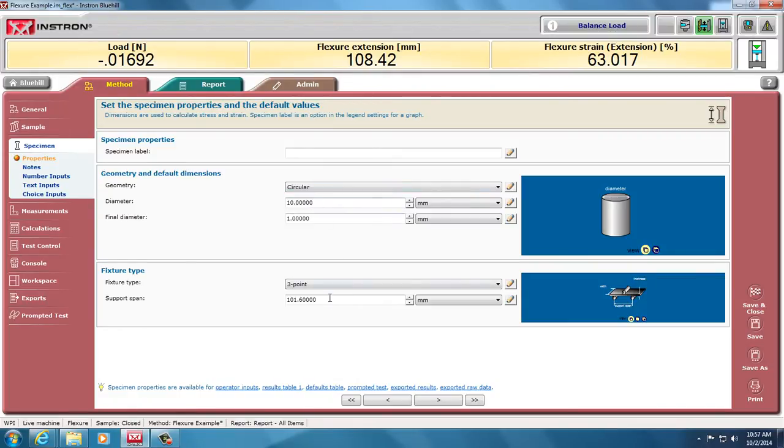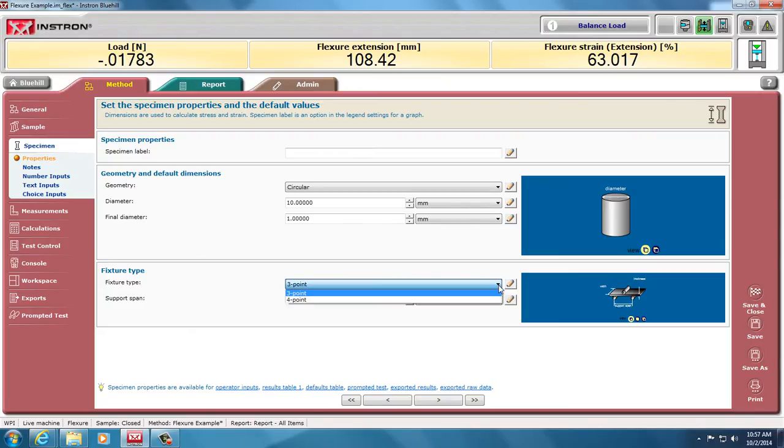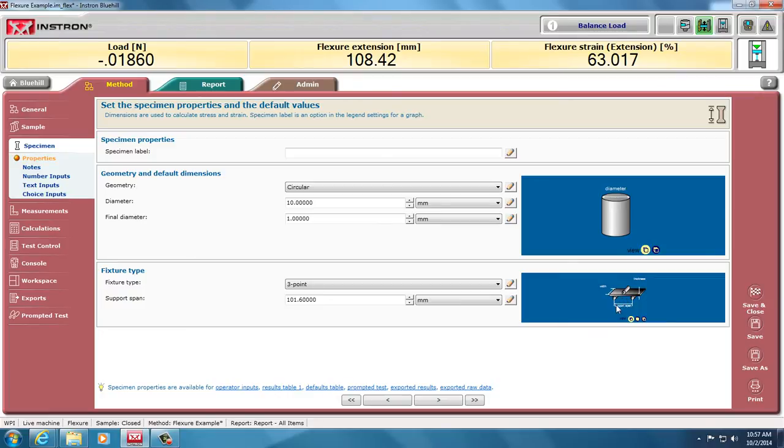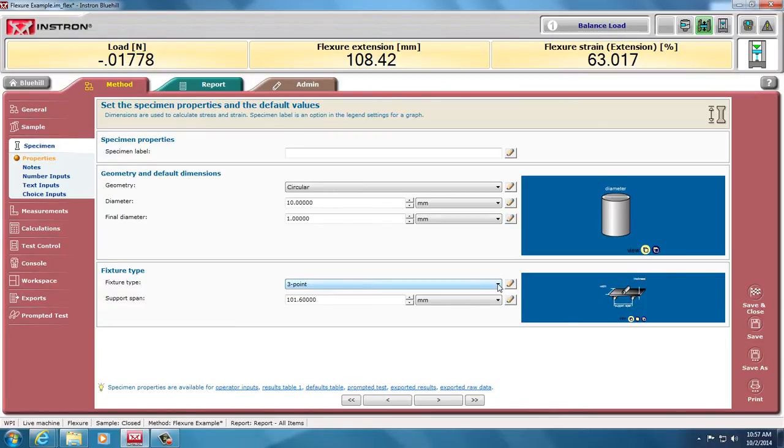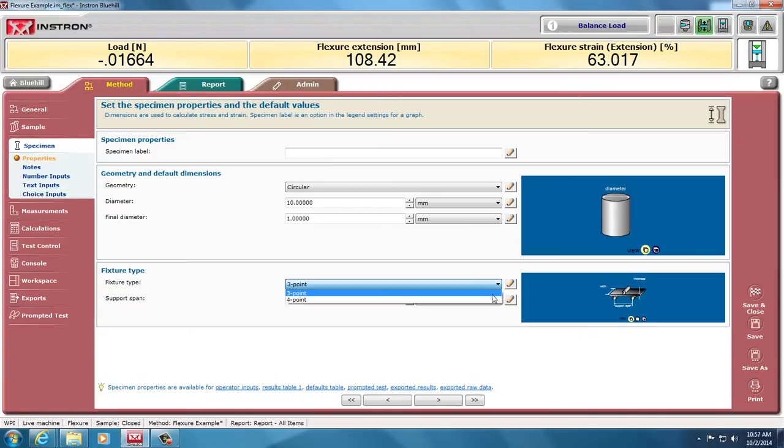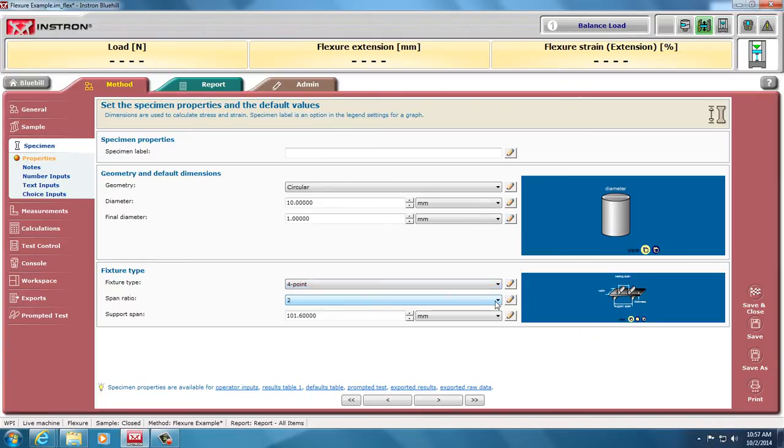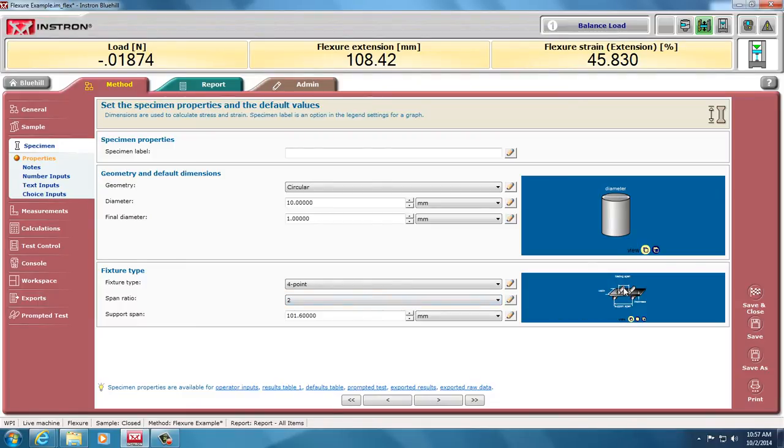You can select your diameter as usual. You can do either three-point or four-point bending. The picture over here shows you what three-point bending looks like. You have a support span, you have your thickness, your width, and then you have your loading that is centered on that. So these are assumed to be three-point bending with your loading centered between the span. The four-point bending, you also have a span ratio, and you have a loading span that you can type in in the actual test, and your support span. Again, these should all be symmetric.